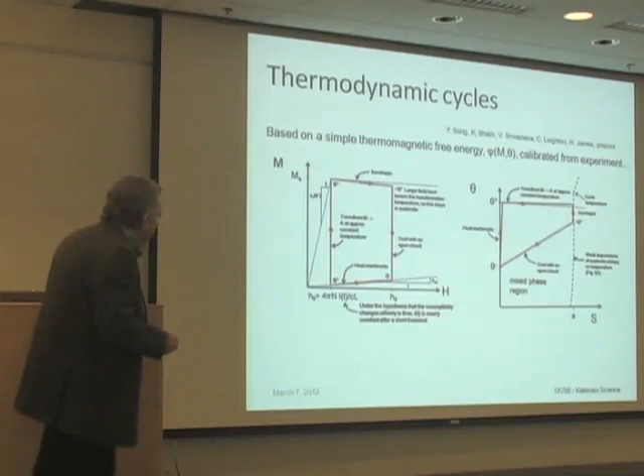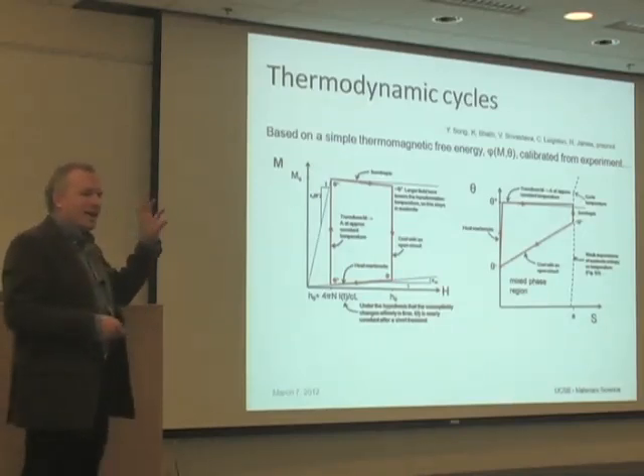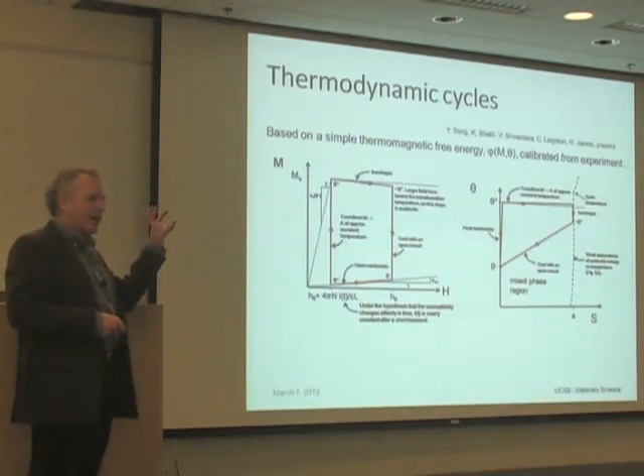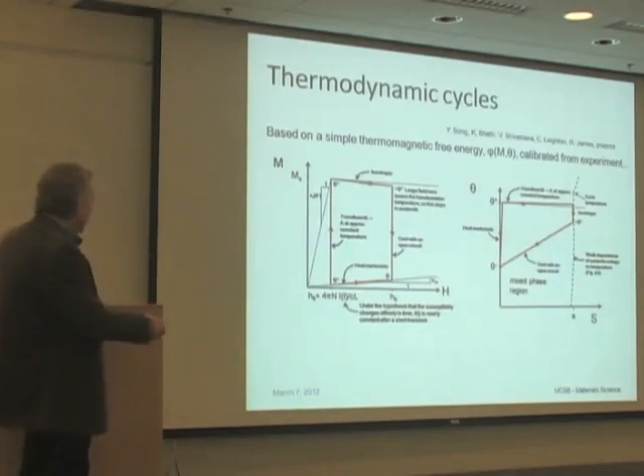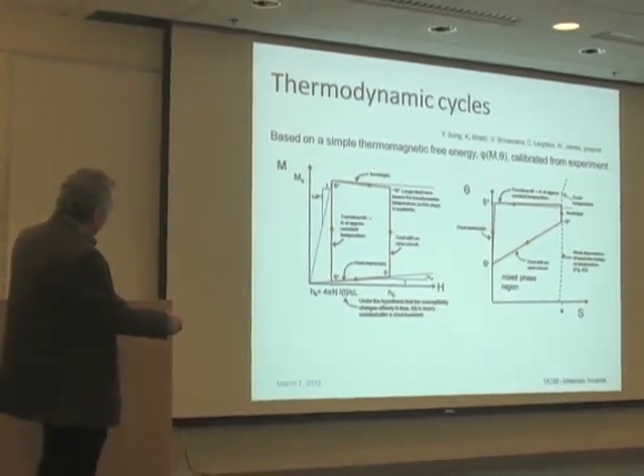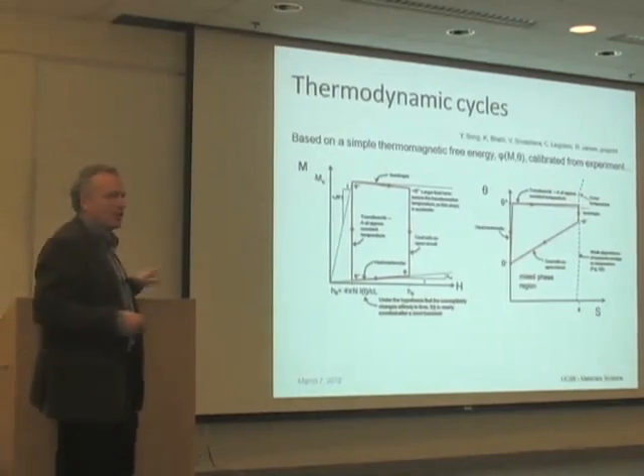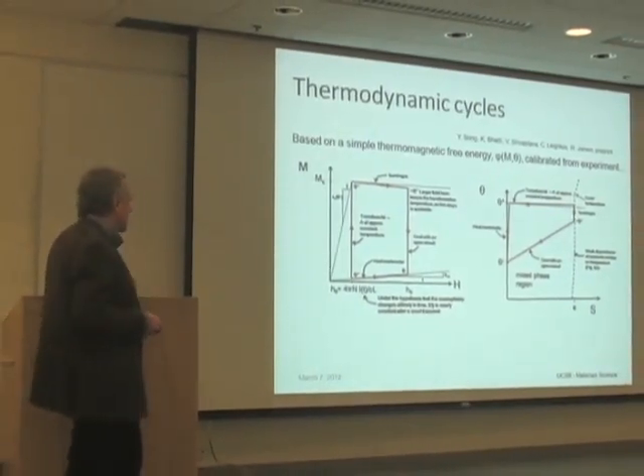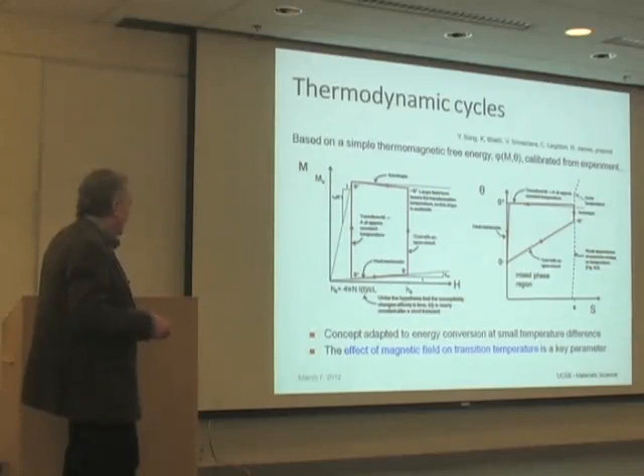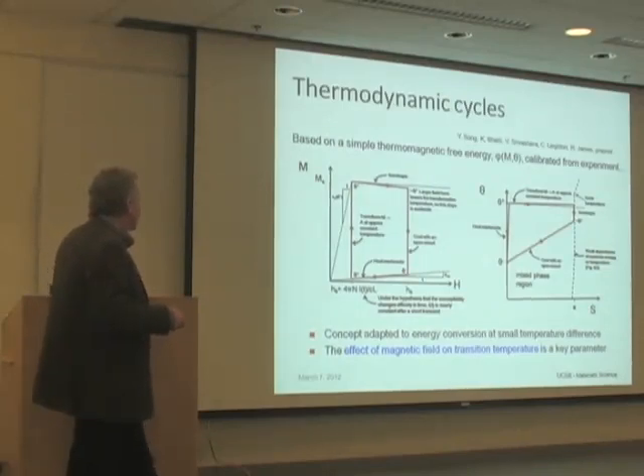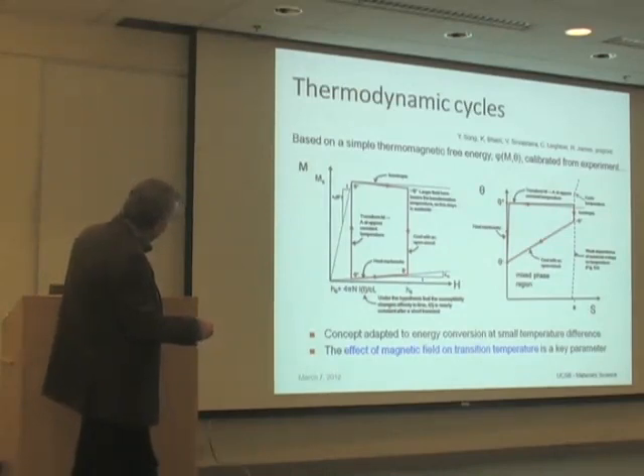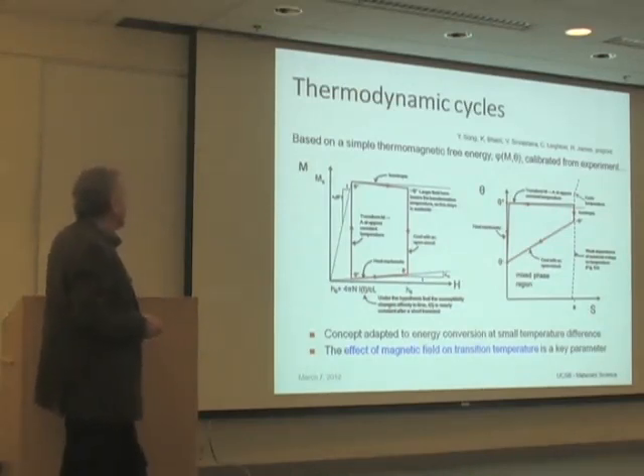And a critical role is played by the fact that the coil then puts a backfield on the sample, reducing the magnetism. And that's this reduction from H0 to this value. That's critically important in the efficiency of this device. And in fact, what you would really like is a big effect of field on transition temperature, and actually going the other way through the phase transformation, instead of jumping down, it jumps up. So somehow understanding this is the critical part about the thermodynamics of energy conversion using this method. I can go into detail if anybody's interested, but I think I'll stop there.